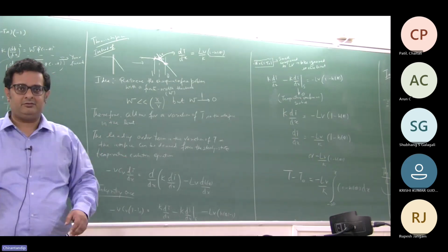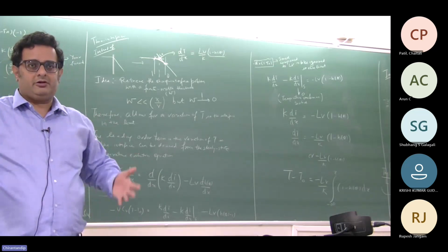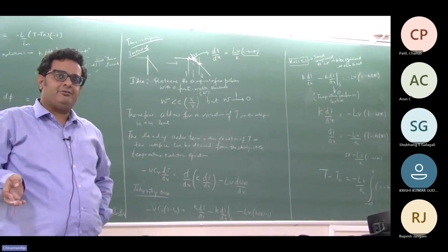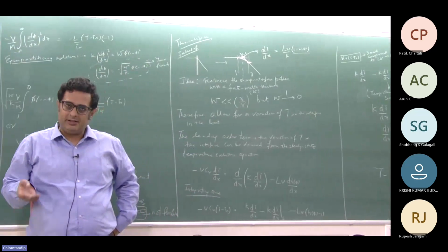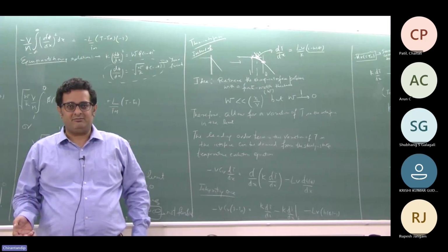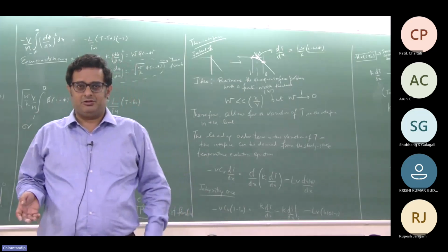So is there any cutoff velocity where trapping actually occurs? There is actually not a cutoff velocity. For any interface width, in principle, you will always have some trapping. It's just the extent of trapping that you will have and that you are okay with. So how do you decide that? It's up to the person who is doing the simulation.